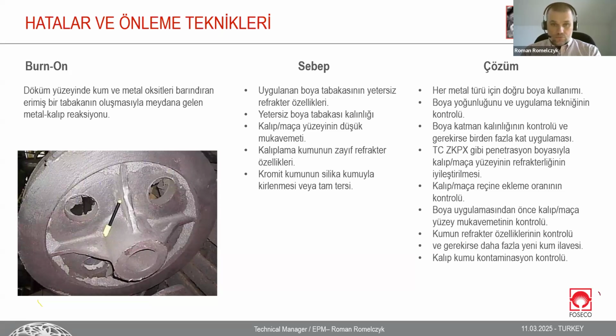In some cases, it need to be used, as I explained, chromite. If not chromite, we can think about use a facing sand only from fresh sand, not mixture between reclaimed sand and the fresh sand. So many possibilities to improve the situation with burn on. Of course, you can also use a pre-coat to help and improve the things.